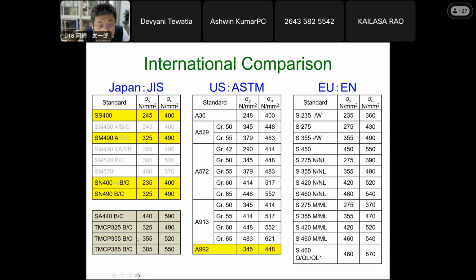Second thing is that for this SA 440 with a yield strength of 440, this is used very commonly for high-rise buildings. And for this one, there is a matching weld electrode. And including such weld products for high-strength steel, there has been extensive study, and there is a quite severe Charpy requirement to qualify for use in seismic applications.